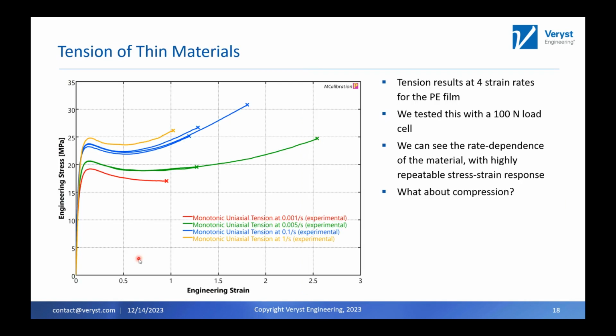Tension testing. We did tension testing here at 4 different rates. We're going to talk about strain rates in a second. In this case, we used a 100 Newton load cell to test these, again using DIC. We went to much higher strains here. Polyethylene famously goes to high strains before failing.